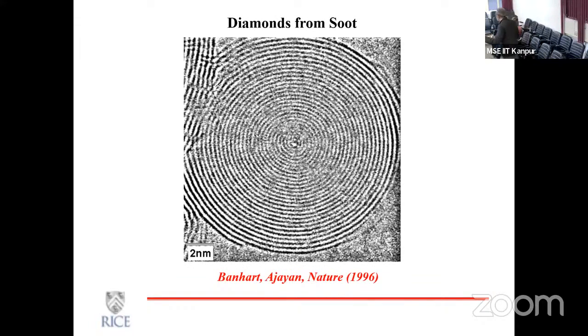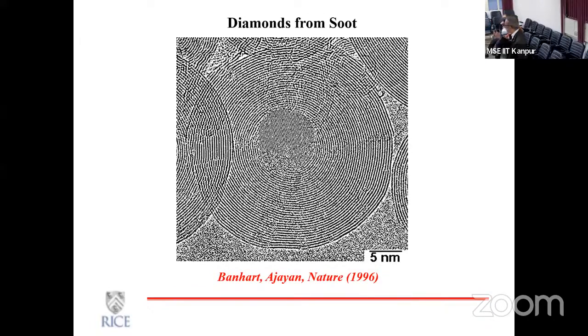I mean, in fact, the compression was so large that if you were to translate to actual physical pressure that you need to actually compress graphite, it'll be 100 gigapascals. So it's a self-assembled structure, but because of this heating involved, the defects were able to play a key role, and the material got self-compressed. In fact, when we continued this experiment to keep irradiating at higher temperature, you start forming diamond in the core without doing anything, right? It's an irradiation-induced formation of this diamond particle in the core of this graphite material.